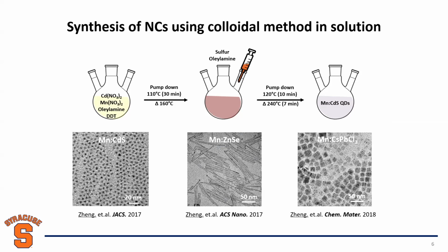But because shape is also very important for properties, we can also make one-dimensional nanowires. For example, this is a zinc selenide nanowire doped with manganese. I didn't show the synthetic method, but for the two samples, I use an almost identical procedure to make them. Exactly the same thing here. For cadmium sulfide, I use cadmium nitrate. Here, I use zinc nitrate. Here's sulfur powder. Here, I use selenium powder. But why in this case do we make spherical quantum dots, and in this case, we make one-dimensional nanowires?